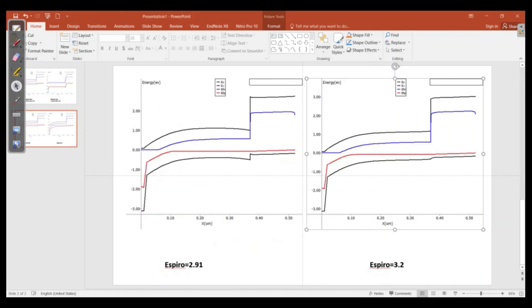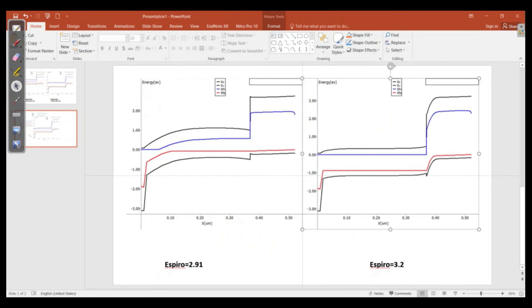Copying and examining the energy band diagram, we can now see that changing the band gap of the material creates a more pronounced spike at the Spiro–perovskite interface. It becomes difficult for holes to overcome this spike, and the performance drops significantly, as we have seen in the efficiency results.